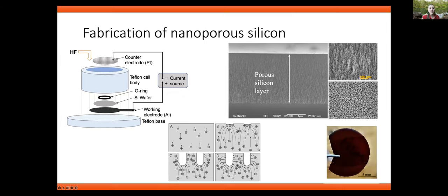And we can also detach those films from the silicon surface. So by etching it at a certain time, at a certain depth, then we will apply a really high electric current, and it will just detach the whole membrane. So this is a porous silicon membrane here on the right-hand side.